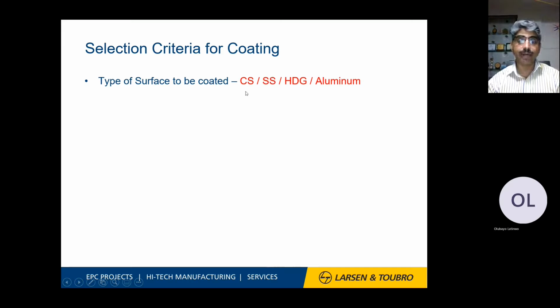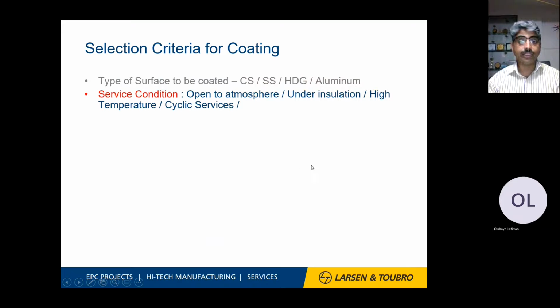Stainless steel and carbon steel equipment and piping are painted for several reasons. Carbon steel, of course, forms an oxide over the surface, so coating is always good for increasing the life. Stainless steel is normally painted because of chloride stress corrosion cracking, to minimize it. So under insulation, stainless steel is always good to paint, or you have to put aluminum foil, which isolates the insulation from chloride environments. Otherwise there are gaps in the insulation, which create problems on the stainless steel surface with respect to time, and improper insulation gaps lead to premature failure of stainless steel pipes.